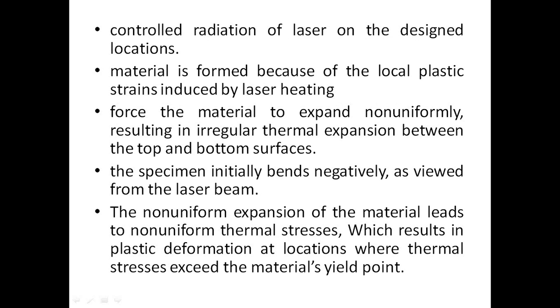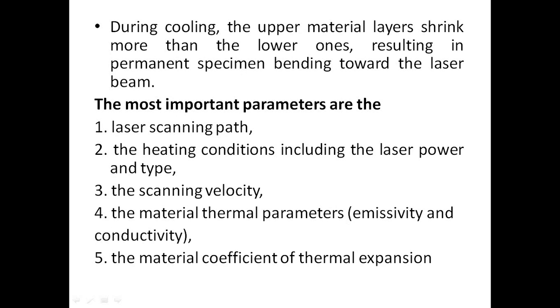The sheet is bent by thermal stress induced by laser irradiation. Controlled radiation of laser on designed locations causes local plastic strains from laser heating, forcing the material to expand non-uniformly, resulting in irregular thermal expansion between the top and bottom surfaces. The specimen initially bends negatively as viewed from the laser beam. Non-uniform expansion leads to non-uniform thermal stresses, resulting in plastic deformation at locations where thermal stresses exceed the material's yield point. During cooling, the upper material layers shrink more than the lower ones, resulting in permanent specimen bending toward the laser beam.